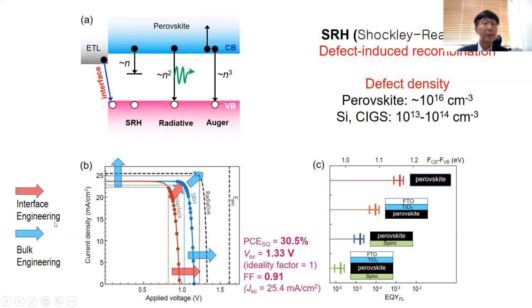And then after that, if you treat the bulk property well with bulk engineering, you can remove the SRH recombination, and at that time you can increase the short circuit photocurrent density, open circuit voltage, and fill factor. Therefore, if you allow only the radiative recombination by removing SRH recombination and interface recombination, then you can expect a 30.5% efficiency with 1.3 volt and 0.9 fill factor.